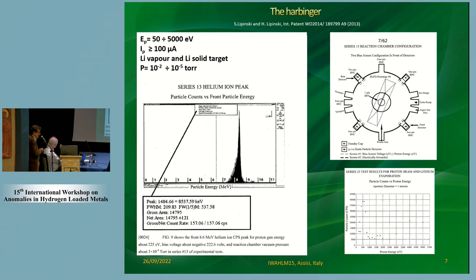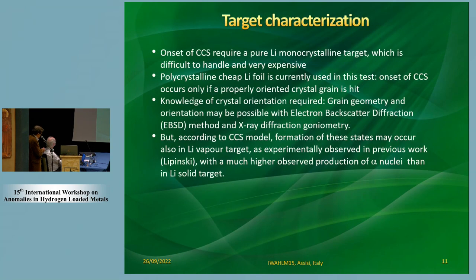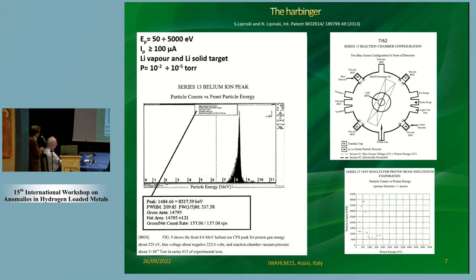We had a harbinger of that. This is the result of a very interesting experiment, done during a long period of tests in several laboratories of the United States by an independent group, Lipinski. During one of those runs, with an apparatus very similar to ours, with the ion source, detectors, etc., they observed a peak in the production of helium-4 exactly at the energy of half of 8.3 MeV, so the energy we expected.